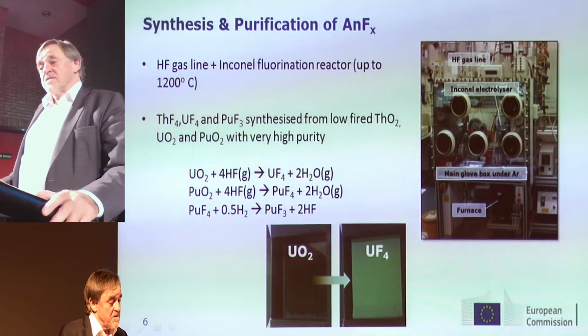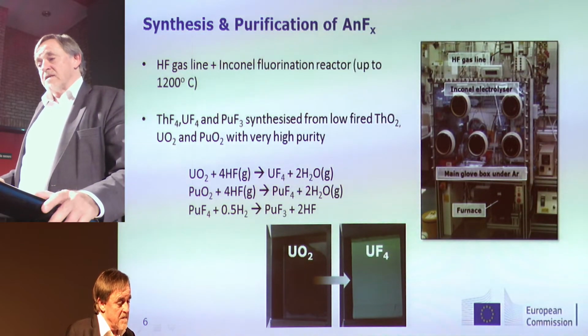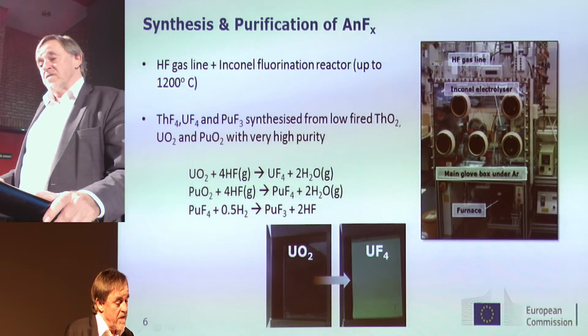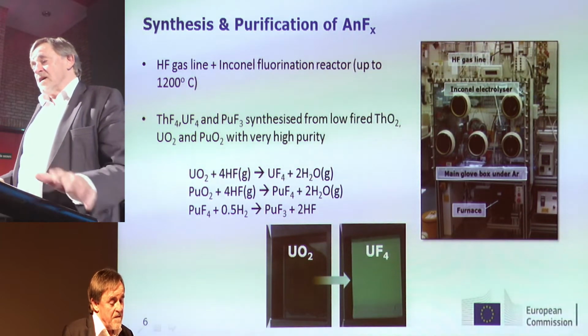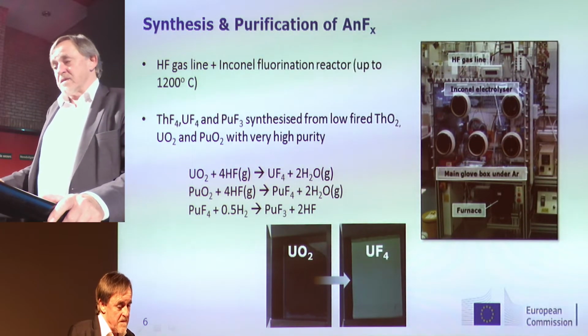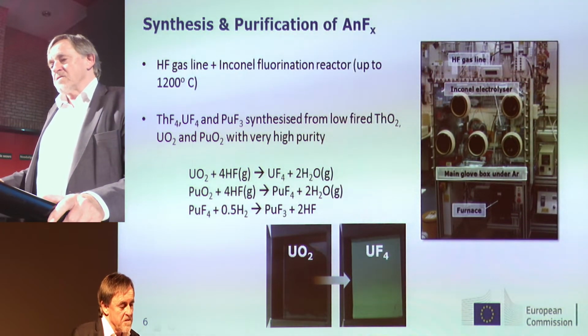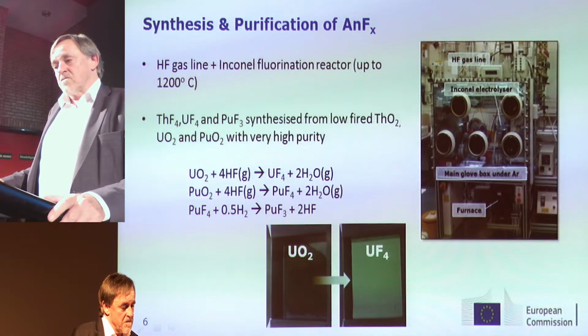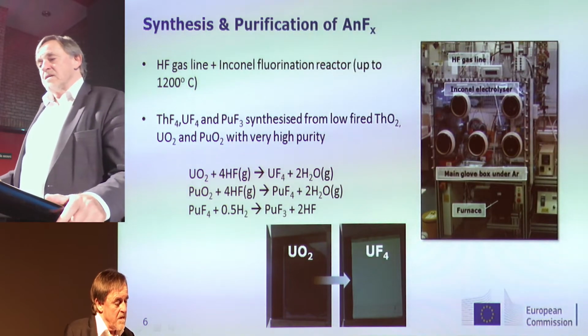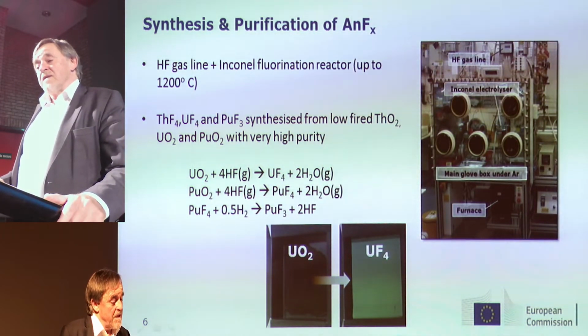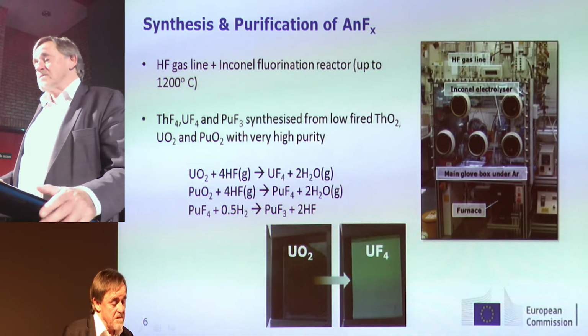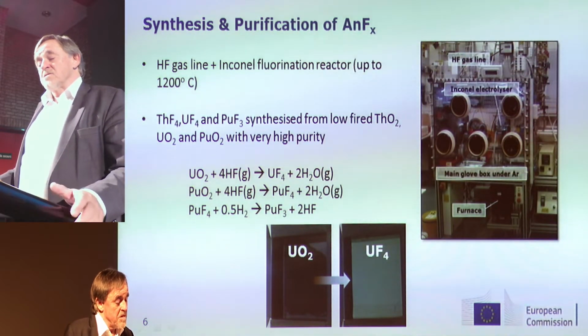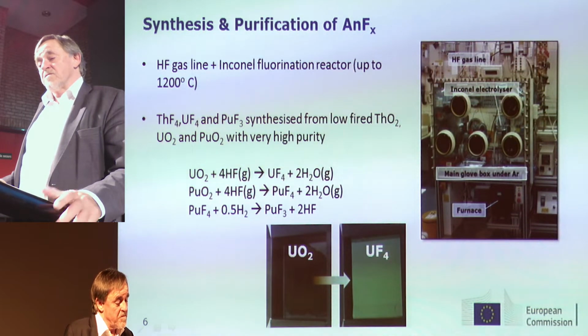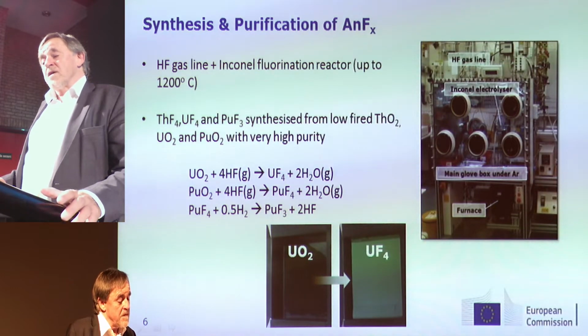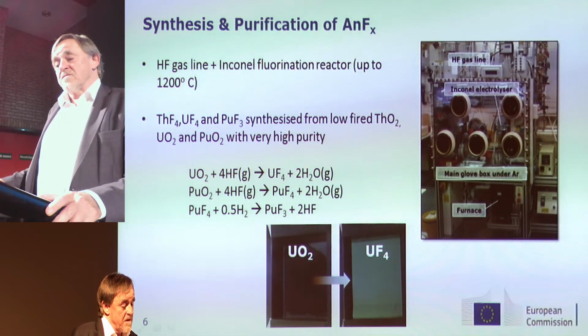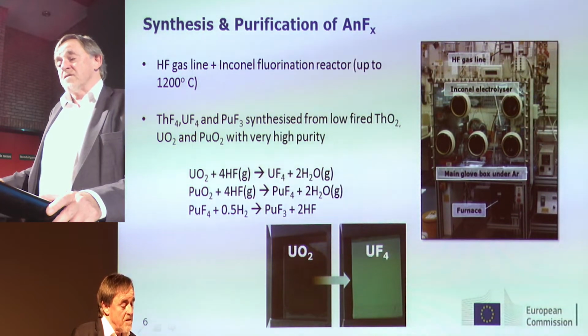So the first step, the synthesis of the actinide fluorides. We have this gas line, as I said, with an Inconel fluorination reactor. The furnace is underneath of this glove box, and the reactor is placed in this furnace from the inner of the glove box. We use as the starting material the oxides, the thorium oxide, uranium, and plutonium oxide, with best possible purity, and then we synthesize the corresponding fluorides with this fluoride line. So we produce, for instance, in the case of uranium, UF4, plutonium, PuF4, but also thorium fluorides, and also with introduction of hydrogen, we can adjust the valency or the stoichiometry of the actinide fluoride.